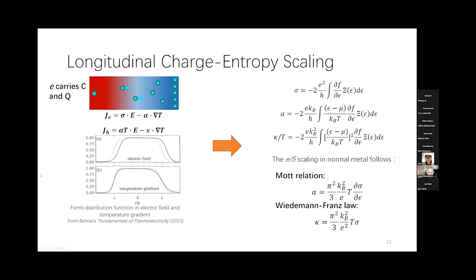anomalous transport coefficient? Before understanding this anomalous coefficient, let's check the longitudinal charge and entropy scaling. So usually we have the Mott relation, which describes the relationship between alpha, the thermoelectric conductivity, and the electrical conductivity. And we also have the Wiedemann-Franz law, which describes a linear relation between kappa, the thermal conductivity, and the electrical conductivity. That is because we make some approximations in the Boltzmann equation. So think about electrons moving in an electric field and a temperature gradient. So the electron can carry both charge and heat.